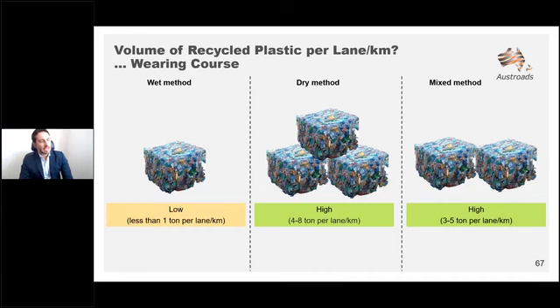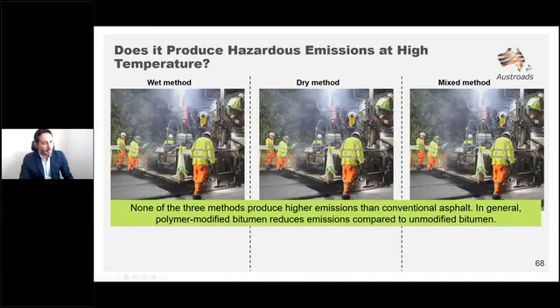Does it produce hazardous emissions at a high temperature? As you can see, I've just decided to put the same photos replicated 3 times for the wet, the dry, and the mixed method, and that's because none of the 3 methods really produce higher emissions than conventional asphalt. Yongjia has presented these results to you today, but also in previous webinars. In general, polymer modified bitumen was found to reduce emissions compared to unmodified bitumen.